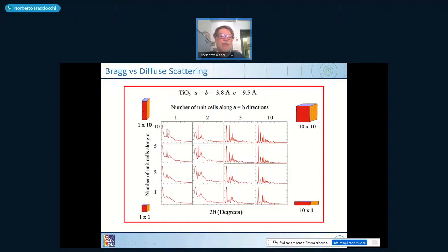And the measure of this peak gives information about the C-axis. Now we go in a different direction. We take this crystal, we make slabs which are 10 by 10 by 1 or 5 by 5 by 1 and so on. Again, you have an increase of the number of peaks, but you have other peaks which come out. These peaks come out because you are increasing coherence in the AB plane and not along C.